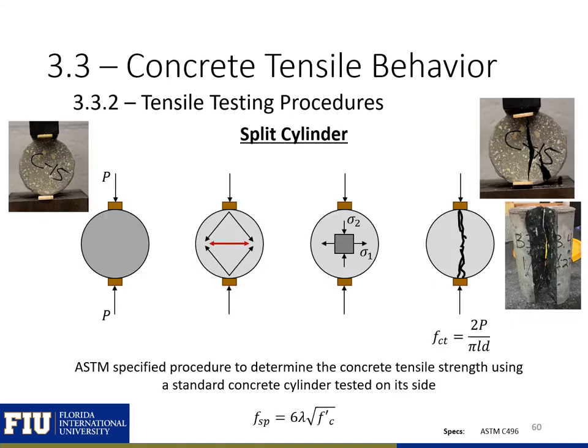Another way to measure the tensile strength of concrete is using split cylinder tests, which are explained in detail in ASTM C496. This test involves a standard 4-inch by 8-inch or 6-inch by 12-inch cylinder placed on its side. A load is applied along the length of the cylinder, which causes splitting stresses to develop in the center of the cylinder, as shown. Load is applied until the splitting crack causes the cylinder to break into two pieces. The load required to cause failure can be used to find the stress along the failure plane. This stress is taken as the tensile strength of the concrete. This test will result in a tensile strength equal to about 6 times the square root of f'c, and is used in tensile strength applications.